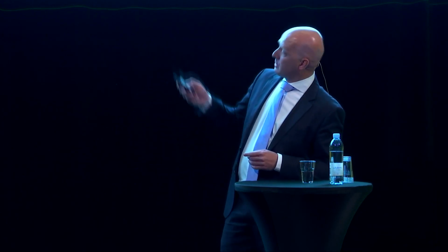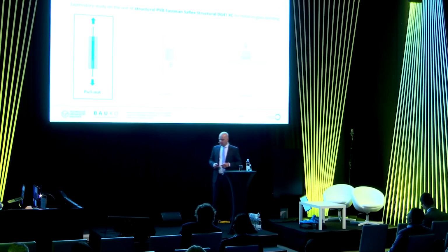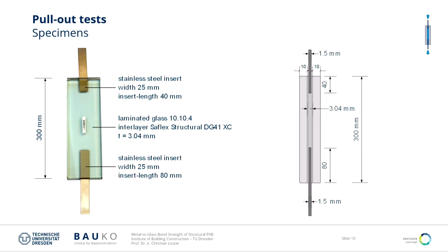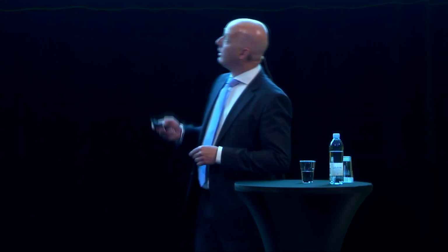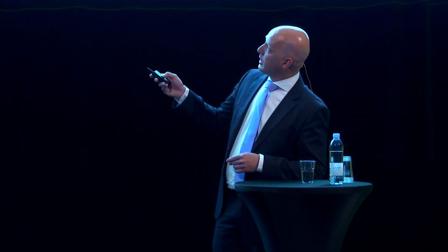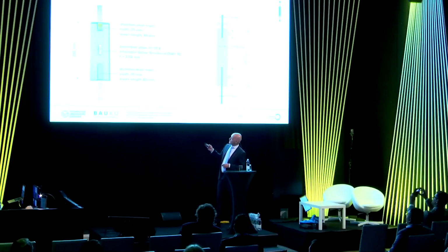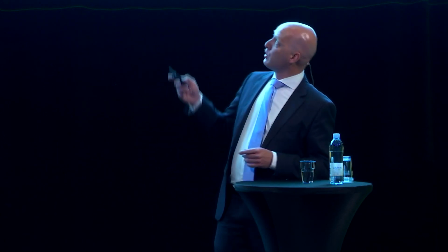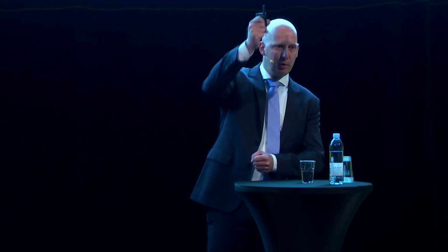We did 3 test series. On the left-hand side, the Pullout tests. I will start with that. In that one, we embed a very thin piece of metal into a laminated piece of glass. You can see that here. So this is laminated glass. This is going into the glass. It's a stainless steel, 25 millimeter wide. This length is 80, and on the opposite side we have a length of 40 millimeter embedded. So just to force that this will be the weaker spot of the specimen, and later we will pull out the embedded steel.